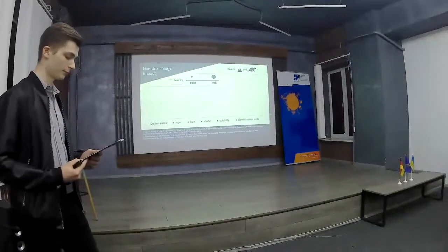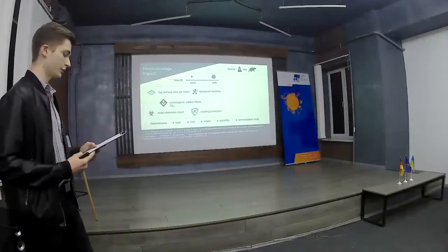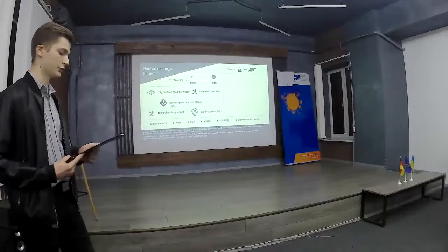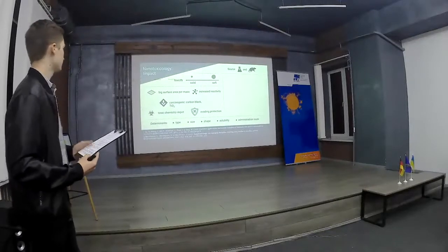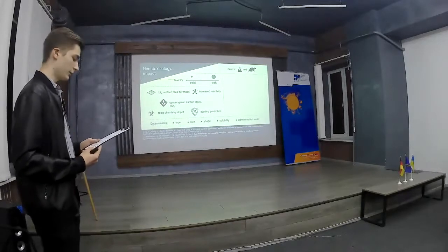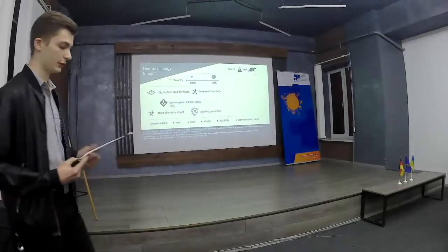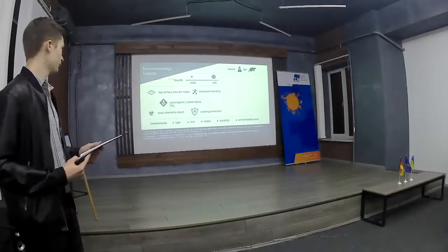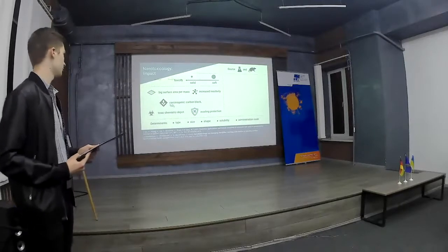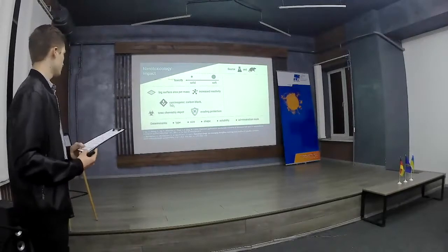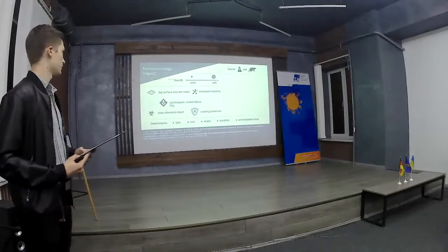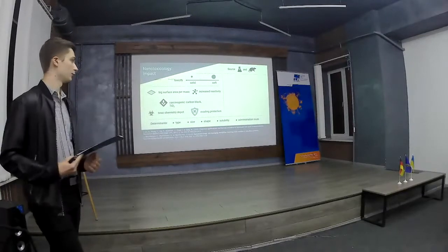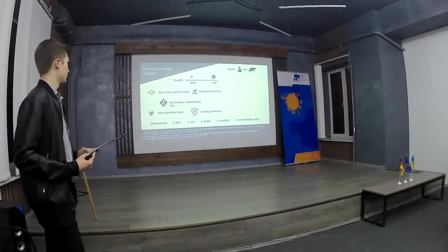Next slide, please. There are several possible properties of nanoparticles. First, small particle size determines extremely large surface area per mass. It in turn determines increased reactivity, so it results in increased inflammatory and pro-oxidant activity of nanoparticles. Certain nanoparticles, for example, carbon black, titanium dioxide, and carbon nanotubes, may be carcinogenic. Some studies do not support this, but they are officially included on the list of potentially carcinogenic structures to humans.